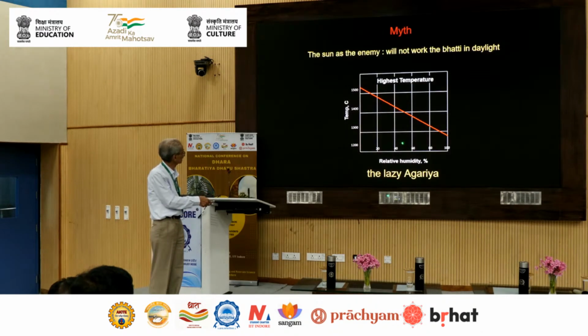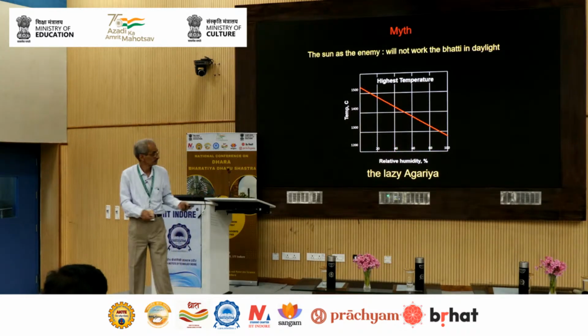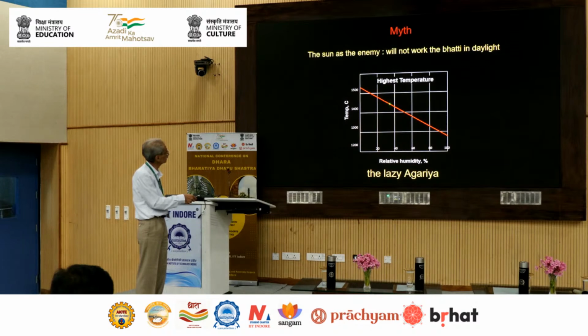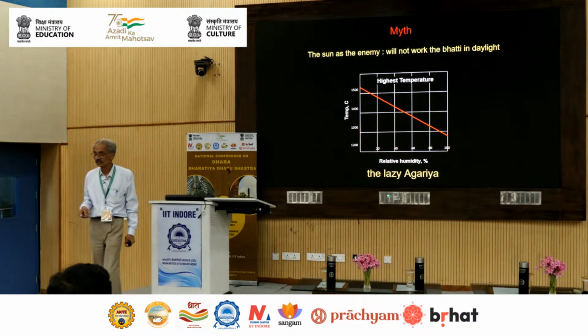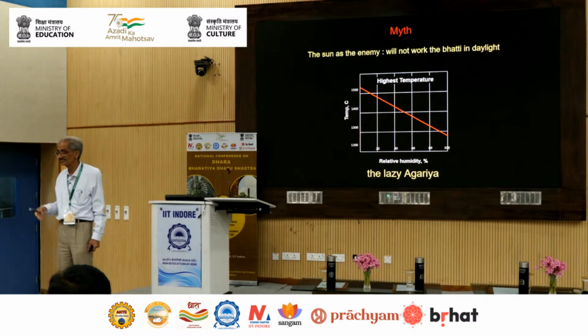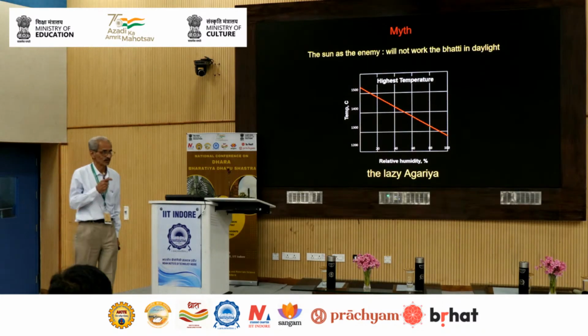Yeah, so as the relative humidity comes down from, let's say, 80% to 40%, that is almost half, the temperature can increase by almost 100 degrees. And it's about 1475 degrees that you need.